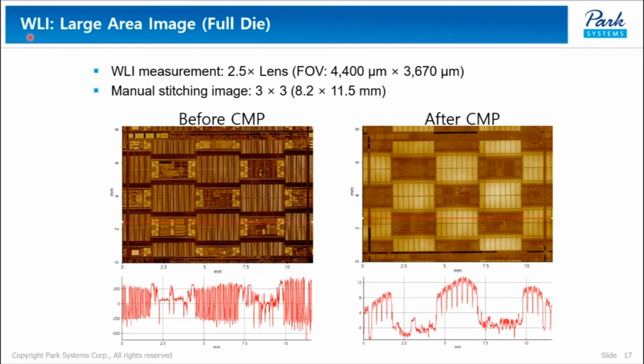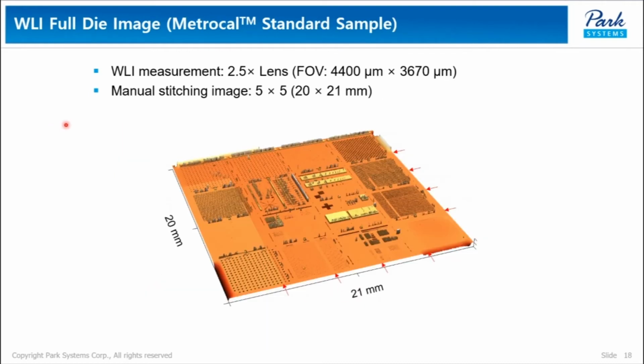WLI can also be used for monitoring the CMP process in a large area. As I emphasized before, WLI on a solid platform with an ultra-low noise floor gives us few nanometer resolution in the z-axis of WLI images. So this is before CMP and after CMP. You can see this difference clearly. With the stitching process, WLI enables us to image a full die 3D mapping. This WLI image was produced by stitching 25 images to show a 20 by 21 millimeter full die map.